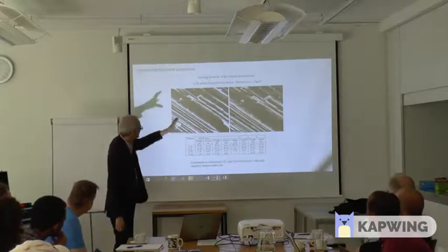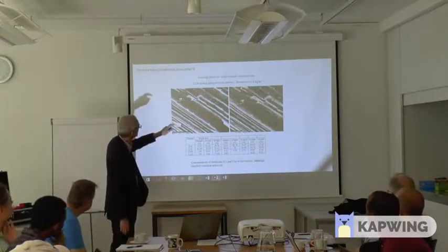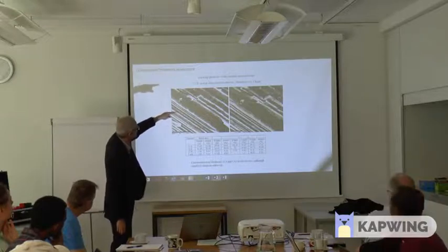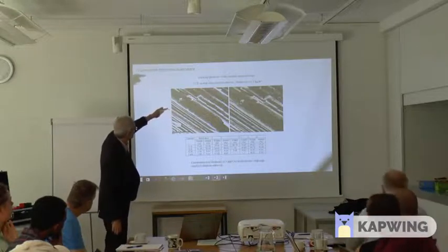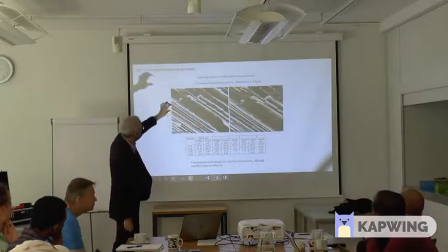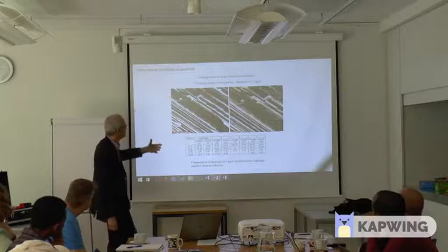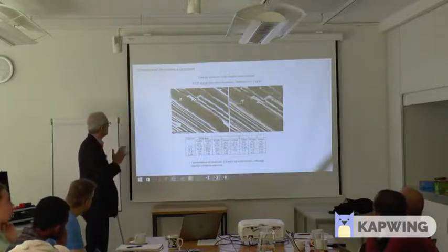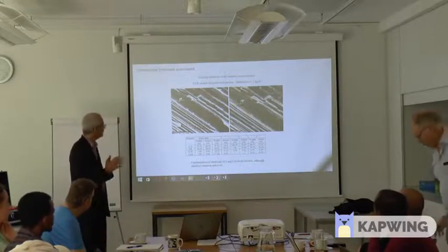I don't know if it's difficult to see from here, but what's red is copper and what's yellow is chrome, and there is an accumulation of those two elements in the vessels of the lignocellulosic structure.